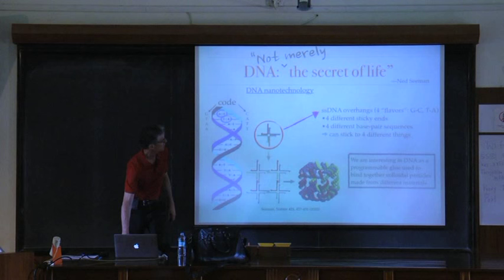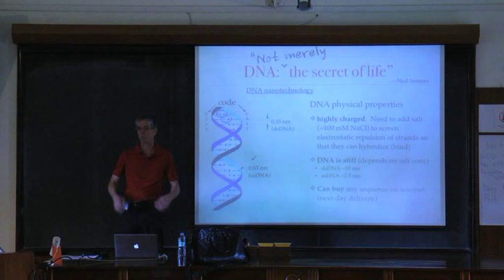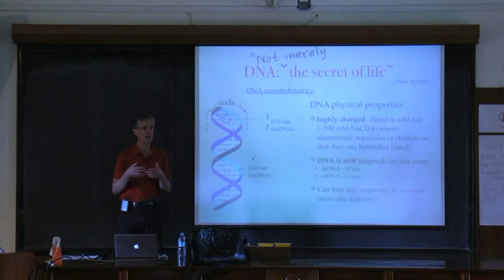We're interested in using this technology as programmable glue. DNA is a polyelectrolyte — it's highly charged. DNA molecules thrown into water without any salt will repel each other and never form a double helix. What you have to do, apropos of our discussion yesterday, is put in some salt. We generally work at about 100 millimolar of sodium chloride, which is sufficient to screen the Coulomb repulsion between the strands so the bases can come together and attach — a process called hybridization.